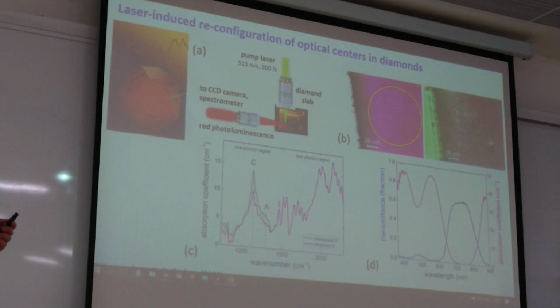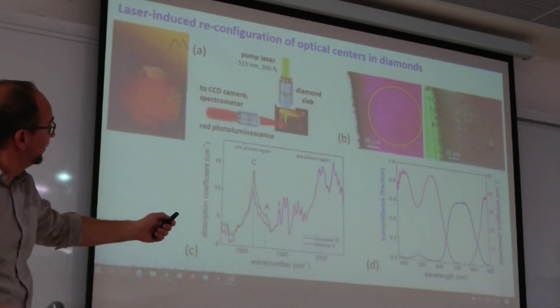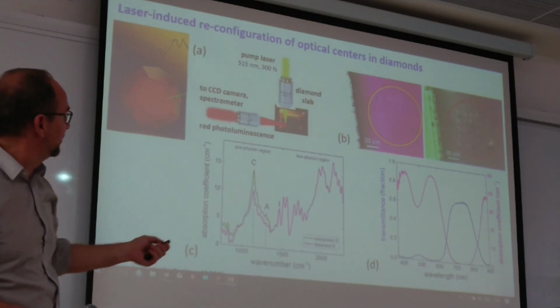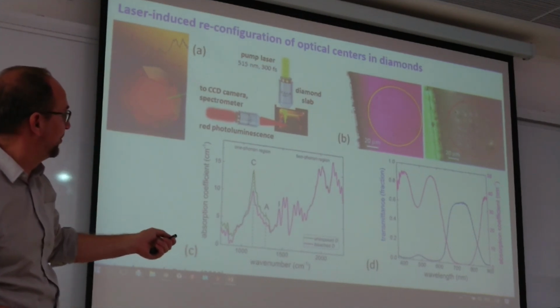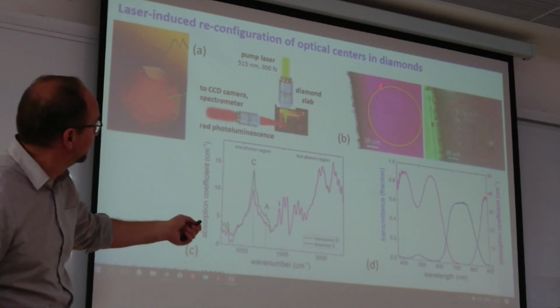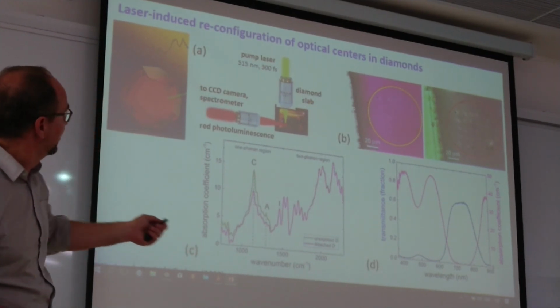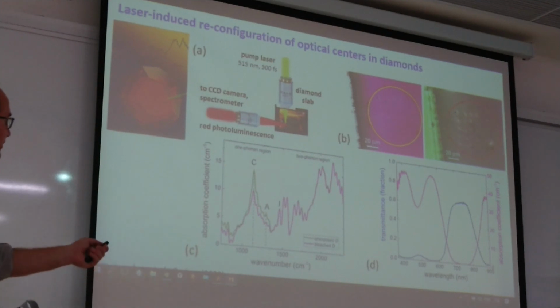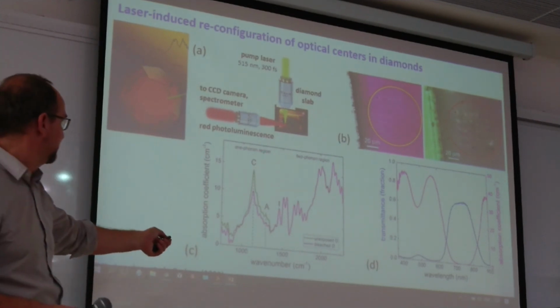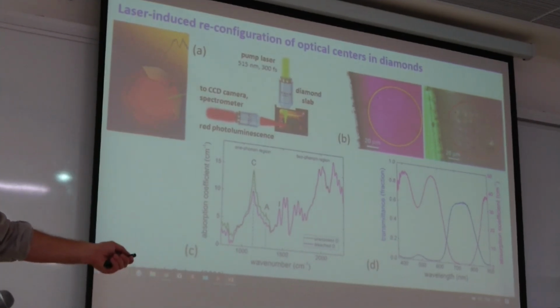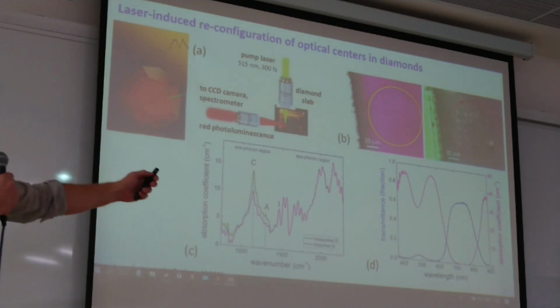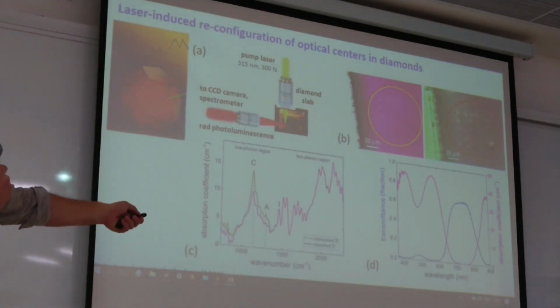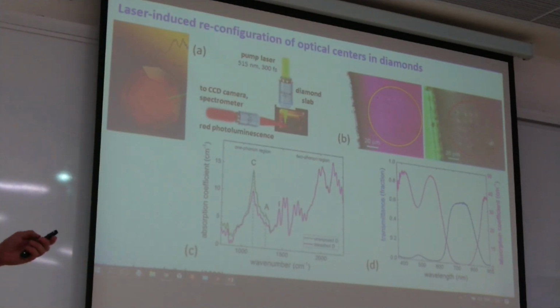And recently in our carbon paper, we have shown that red diamonds can be bleached by femtosecond laser. So it's initially a red one, but it can be bleached. And in the infrared spectrum, we can see that C and A centers, which make this red color, decreased a little bit. There are the same changes in optical transmission, which occur as these marks.